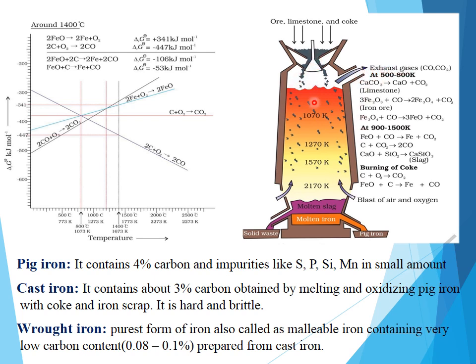As soon as the charge is fed, a hot blast of air is passed, due to which the carbon, the coke which is present in the blast furnace, combines with the oxygen to produce carbon dioxide. Initially the blast furnace temperature will be maintained around 1500 Kelvin, but since the formation of CO2 is an exothermic reaction, the temperature rises to around 2200 Kelvin.